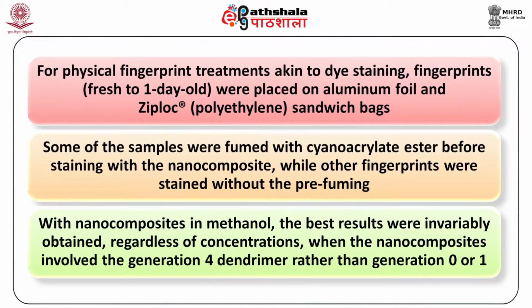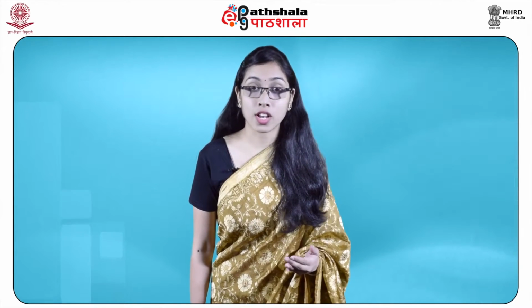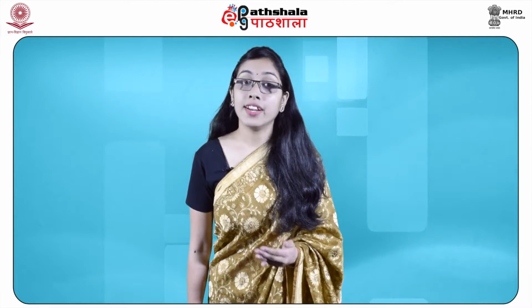For the development of physical fingerprints, a treatment akin to the dye staining procedure, fingerprints that were fresh to 1 day old were placed on aluminium foil and Ziploc sandwich bags. Some of the samples were fumed with cyanoacrylate ester before staining with the nanocomposite, while other fingerprints were stained without pre-fuming. With nanocomposites in methanol, the best results were invariably obtained, regardless of the concentrations, when the nanocomposites involved generation 4 dendrimer rather than generation 0 or 1. This dendrimer is the focus of the chapter that follows, the nanocrystal composition for the detection of fingerprints.